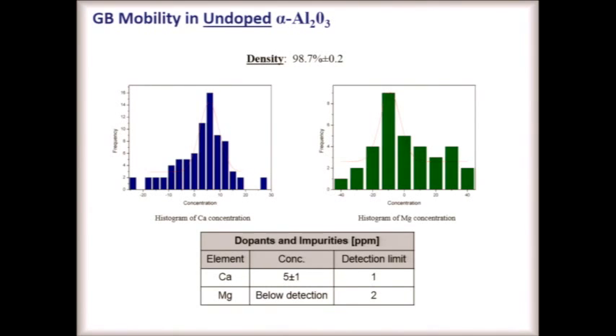This is, Frank, our calcium concentration and magnesium concentration in the undoped materials, okay? The mean is 5 ppm of calcium, which is actually right in spec with the supplier who did ICP of the powders that they gave us. So we didn't make it any dirtier, but this is as clean as the powders that we were able to get commercially. Magnesium was below our detection limit of 2 ppm.